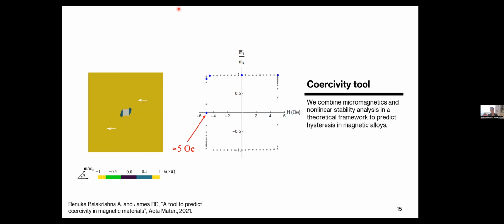And for iron, for example, we're able to predict that in the presence of a nonlinear disturbance or a localized disturbance, the coercivity is 5 oersteds. It's still an order of magnitude larger than what we see in experiments. And there could be reasons as to why we see that, because we assume a single crystal, we assume perfectly smooth interfaces, we just introduce one localized disturbance or a defect. But the positive side is this is giving 2 orders of magnitude a better prediction than the current methods that are used to predict coercivity or to measure magnetic hysteresis.